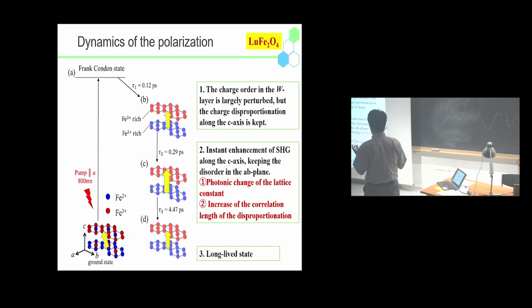We cannot say a definite scenario, but we can consider two reasons. One is the photonic structural change by the photo excitation. Some structural change occurs by the photo excitation, and that results in the increase of the chi2 of these materials. The second origin is some increase of the correlation length of the charge disproportionation.